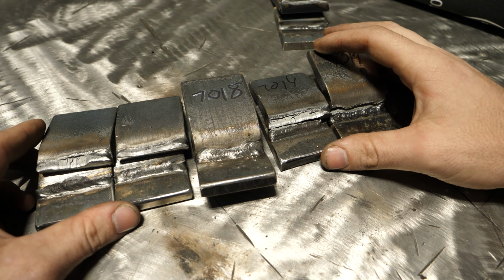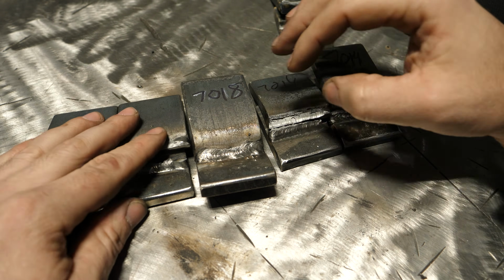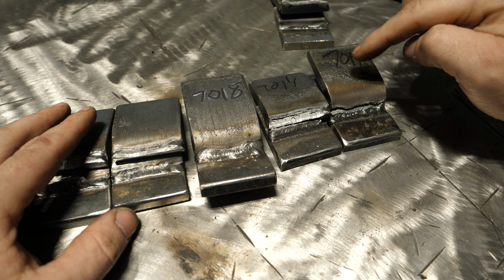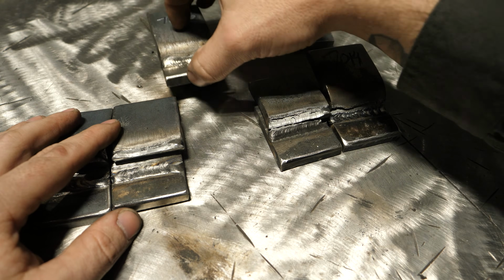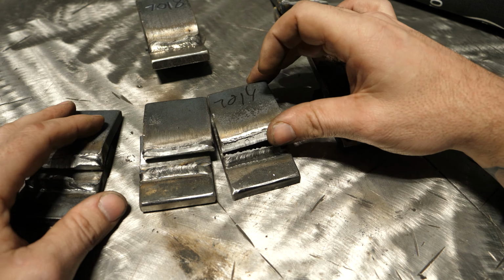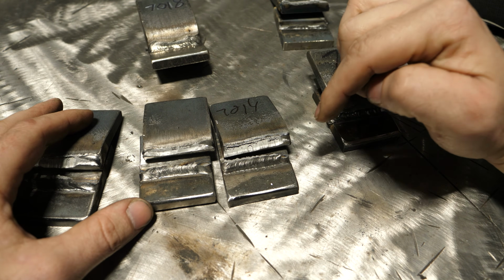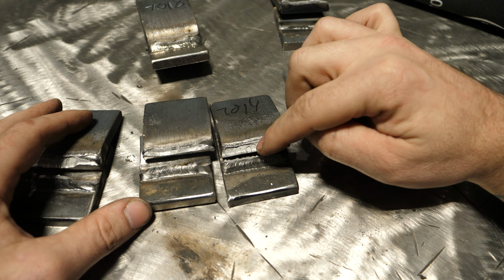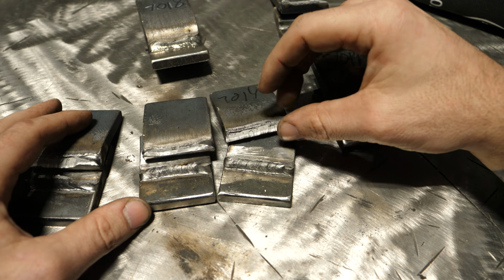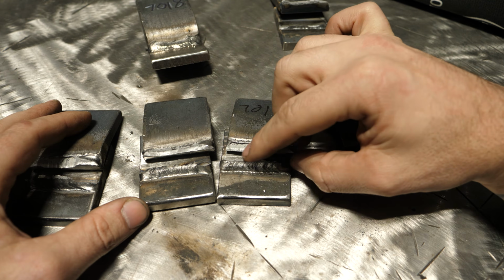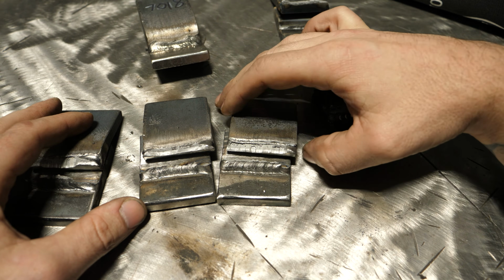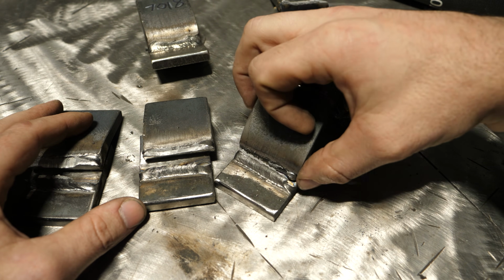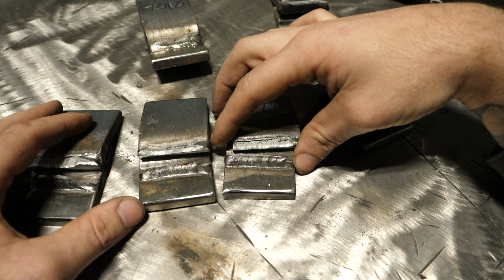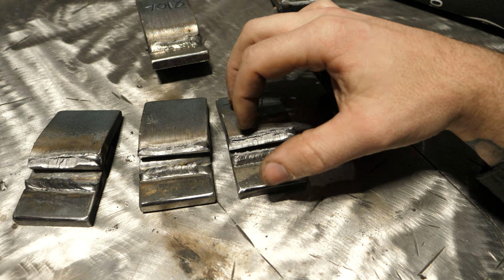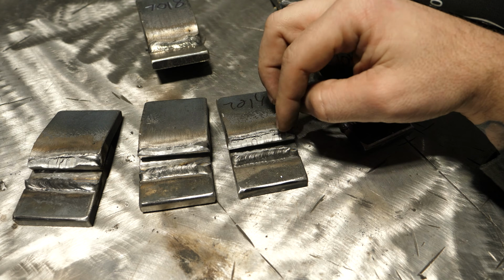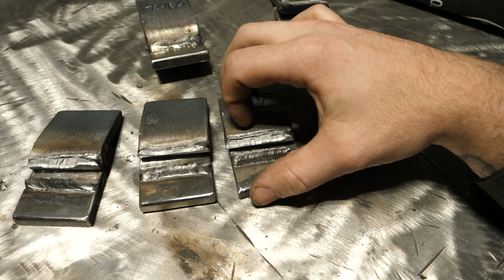All right, so let's compare these. These are 7024, a 7018, 7014, 7014. Let's just compare these two. So the 7014, I've done at least, I think, six of these now. They all break in the same manner, roughly, which is they tear a big chunk out of the plate. The crack may start down here in the corner where the weld is the thinnest and then propagates, but realistically, that's how all of these welds will likely do, but it tears out the plate.